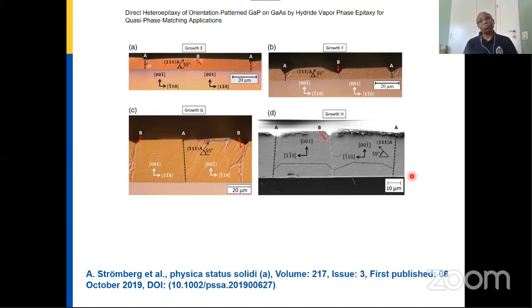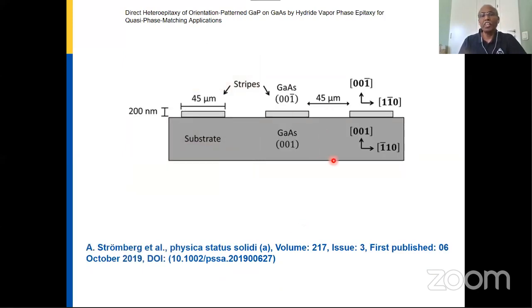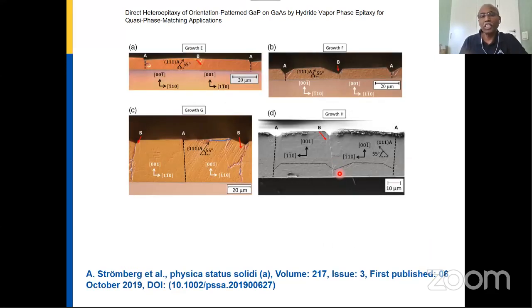And this is the latest result we have. They are not really fantastic enough, but we have at least achieved some kind of boundary separation. When you are trying to grow like this, it happens that you do not get the boundary separation between these. If you don't have the boundary separation, it will not be useful. So at least we have achieved the boundary separation, but they are not thick enough. We need to grow at least to 500 micrometer, and this is only around 40 to 50 micrometer, and they are not vertical enough. So we are optimizing this growth, and we are working on this.